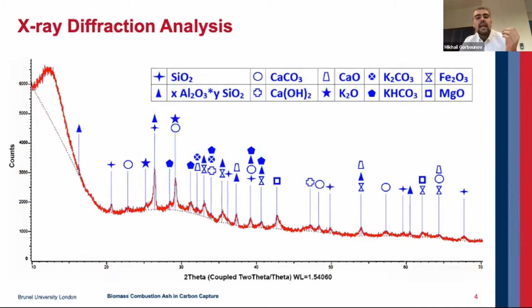And the key thing is that it has only one potassium atom, and this allows for an additional carbon dioxide molecule to be fixed on the other K atom from the original molecule. Similarly, K2O is also a noteworthy compound. Again, in the presence of moisture, the reaction with CO2 will lead to bicarbonate formation, and therefore one molecule of the original substrate would allow to capture 2 molecules of CO2.